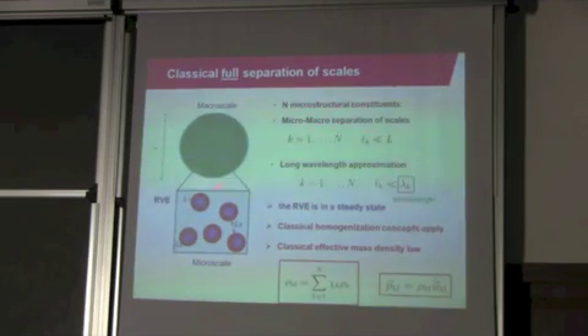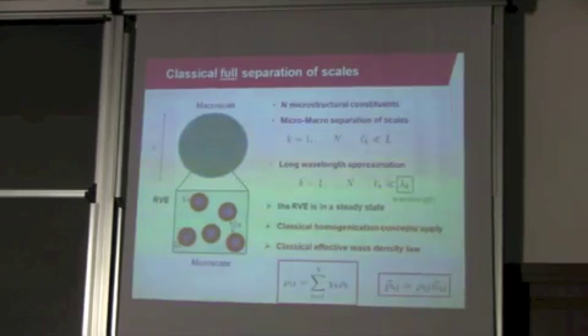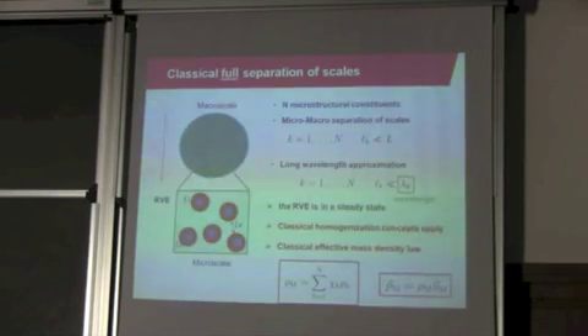What that principle says is, first of all, if you have several micro-constituents of particular characteristic sizes L, all of them have to be much smaller than the characteristic size of the macroscale, which can be either the macroscopic size or the characteristic wavelength passing through the macroscopic size. Actually, I should also add that the size of a statistically representative volume element also has to be much smaller than the macroscopic characteristic size, but this is not relevant for this work, so I omit that part. On top of that, the so-called long wave approximation has to hold. That says that the wavelengths traveling through each of these microstructural constituents, so the representative wavelengths of the problem of interest, have to be much larger than their size.